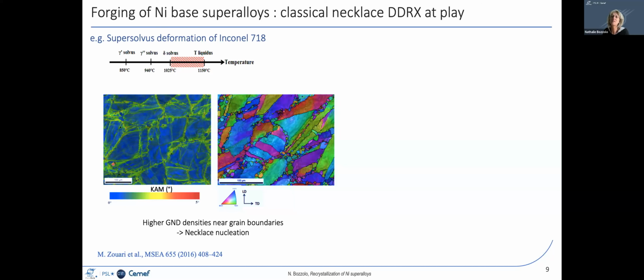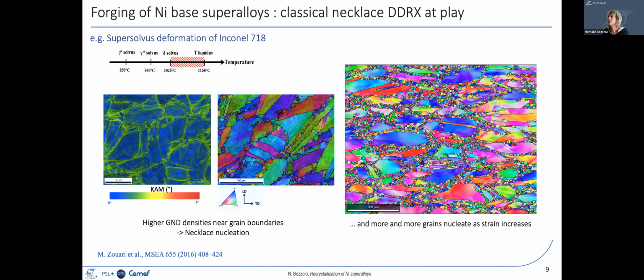This is due to the plastic strain incompatibility. So the dislocations are preferentially stored along the boundaries, and therefore this is where the new grains will form, because they appear where the stored energy level is the highest. So indeed, if hot deformation goes far enough, then you would see new grains appearing at the former grain boundaries. And if you keep deforming to higher and higher strain levels, then you would see more and more of these new grains forming and consuming the deformed matrix. This is a very classical mechanism, the necklace dynamic recrystallization, discontinuous dynamic recrystallization, which is at play here.